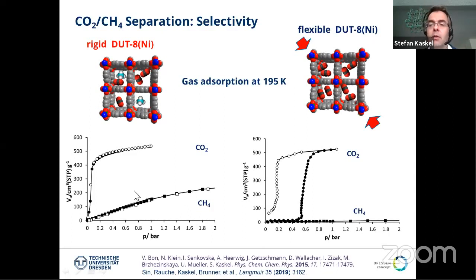Of course, these are single component adsorption isotherms. This behavior is totally different when you look at a flexible variant, the flexible DUT-8 nickel. Here you see, when you look at the methane adsorption isotherm, the methane cannot open the pore. So there's no methane adsorbed. Only CO2 can adsorb inside the pore and can open the framework. And of course, this in theory should give an infinite selectivity.